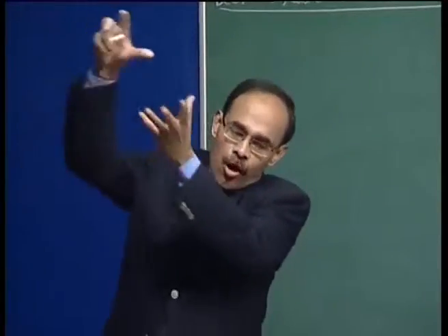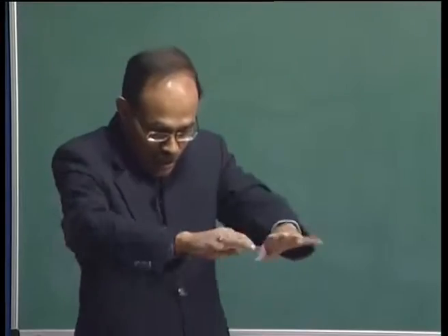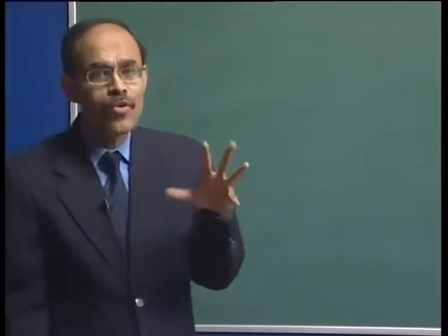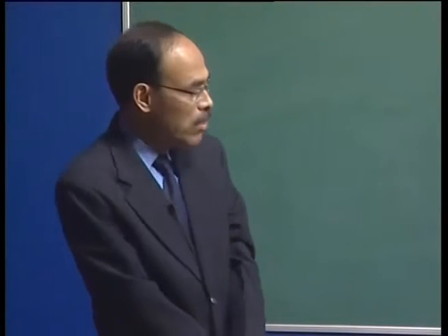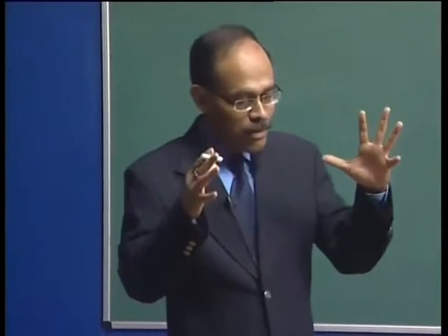It is going to be dropped through a chute, pointing to the region where the stream from the furnace is entering the ladle, the impact zone, such that the aluminum can be entrained subsurface. So the scientists knew that we have to somehow keep the aluminum submerged, and only then can we improve the recovery of aluminum. We have to stop the contact of aluminum with the slag or with the environment, and aluminum has to come in contact directly with the metal. So it has to remain subsurface.